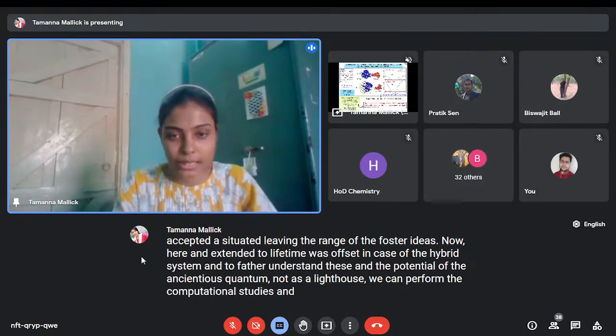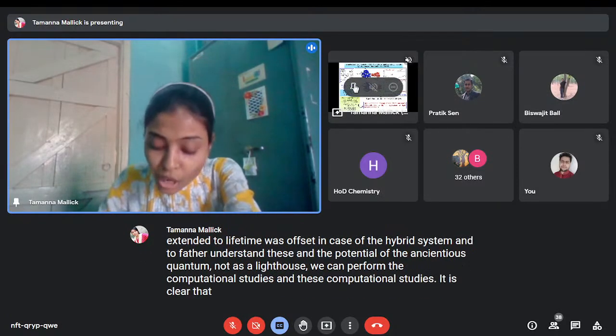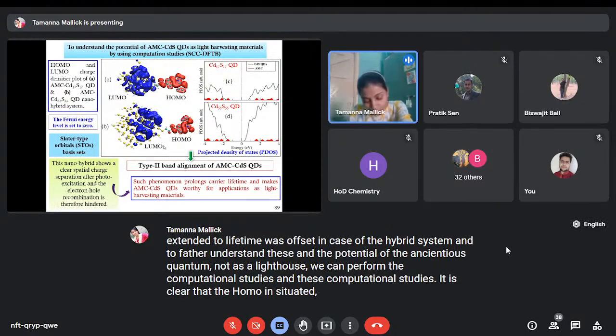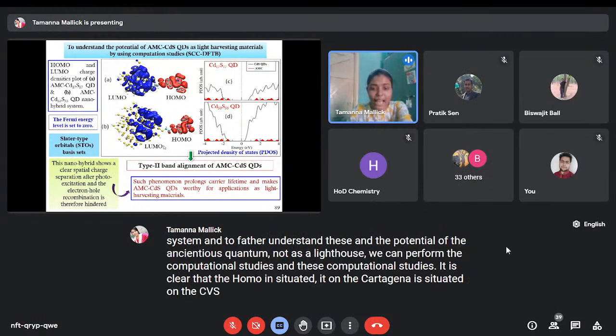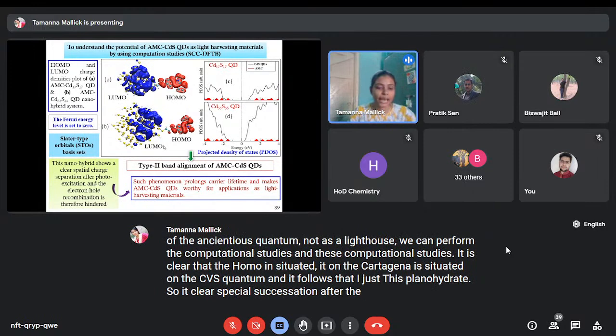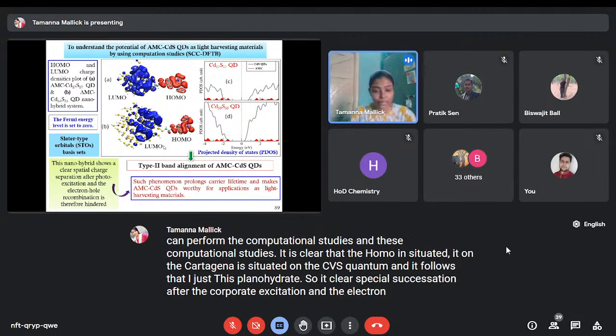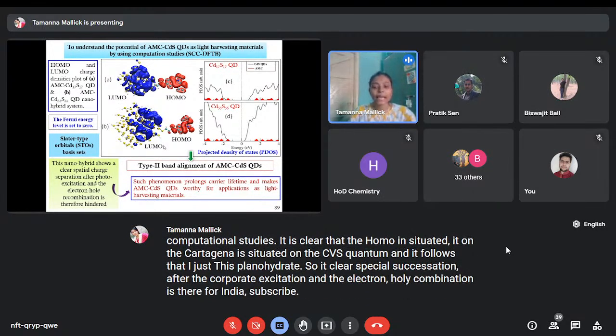From these computational studies, it is clear that the HOMO is situated on the carbazole moiety and the LUMO is situated on the CdS quantum dot, that is the acceptor, and it follows the type 2 band alignment of the AMC-CdS quantum dot. This type of band alignment also reflects from the projected density of states. These nanohybrids show a clear spatial charge separation after the photo excitation, and the electron-hole recombination is therefore hindered. Such phenomena prolong carrier lifetime and make the AMC-CdS quantum dot worthy for application as light harvesting material.